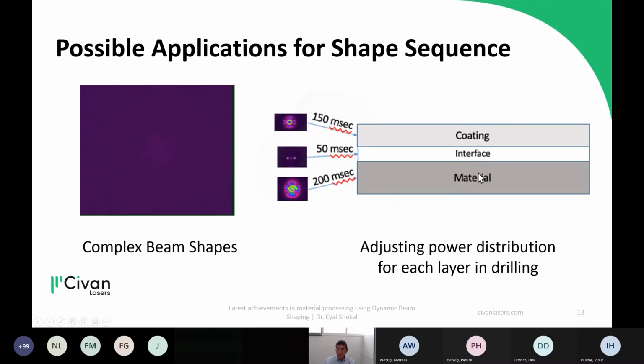So for example, if you have here a metal that is coated with some coating, let's say ceramic coating, and they are glued together, and you want to drill through this. So of course, the ceramic has completely different properties than the metal. So you want to optimize a beam shape that is different for the ceramic than it is for the metal. And in the interface, many times there are cracks and separations that are created when you drill through it. So maybe you want to have a different beam shape when you go through the interface to protect this sensitive interface region, to avoid these cracks and separation.